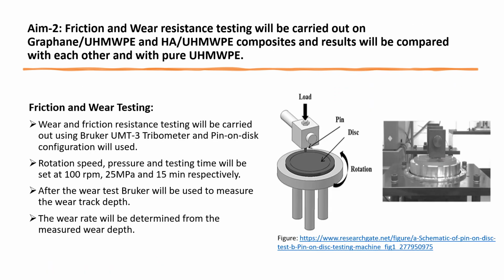The second aim of my proposal is the friction and wear testing, which will be carried out using the Bruker UMT3 tribometer, and a pin on disc configuration will be used. The rotation speed will be 100 RPM and the time will be 15 minutes. Then the Bruker will be used to measure the wear track depth, and the wear rate will be determined from the measured wear depth.